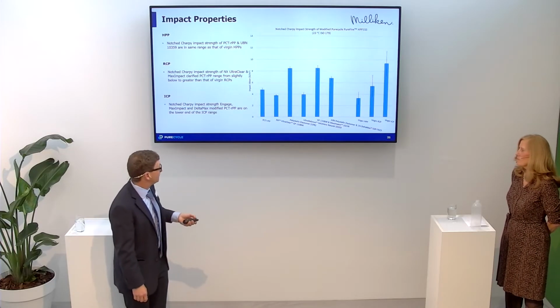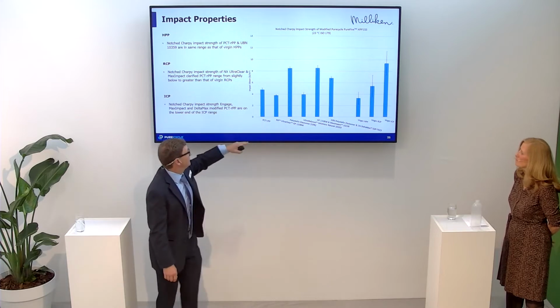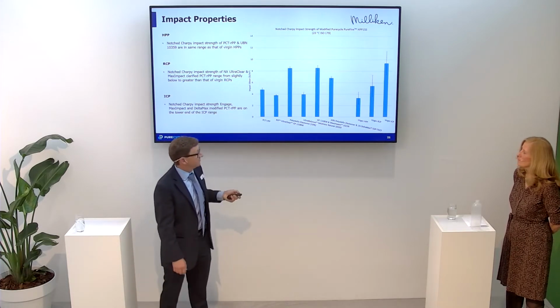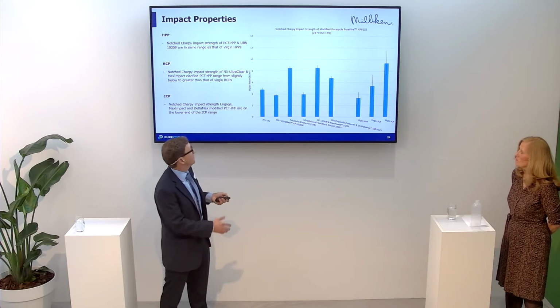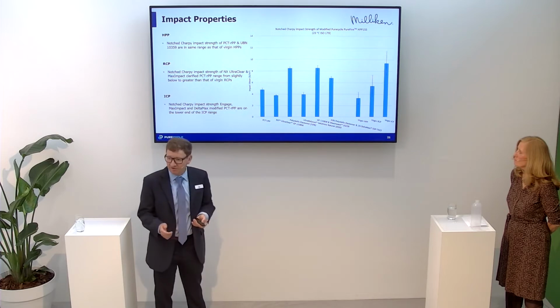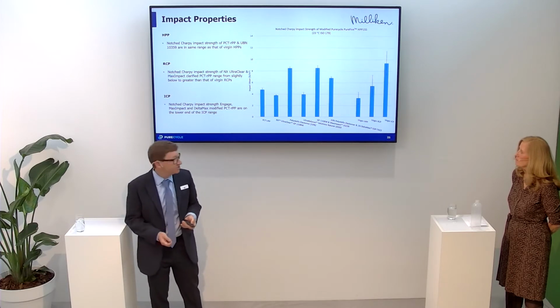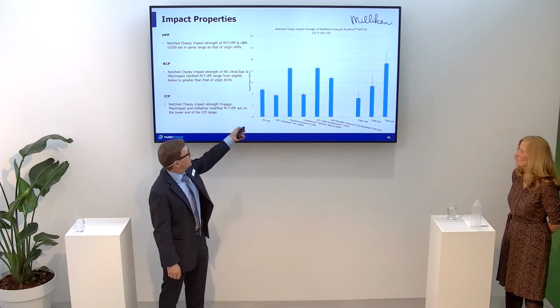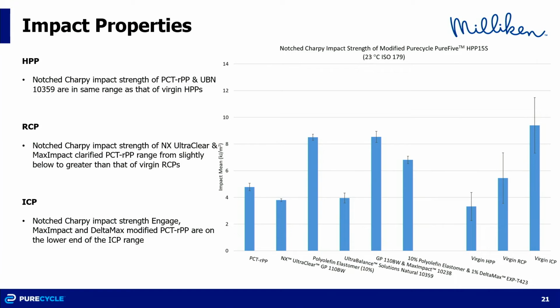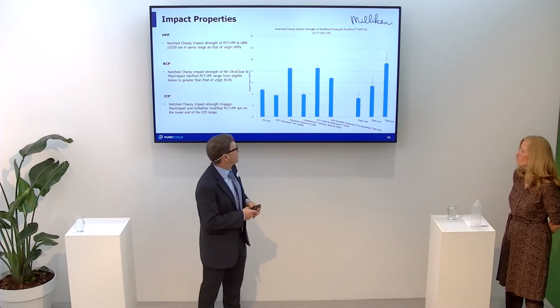Finally, impact properties. The material as received with the nucleating package is a little better than a homopolymer, at about 5 kilojoules per meter squared in a notched Charpy at room temperature. The clarified sample is a little bit lower, at 4. But again, it's still in the range of virgin random copolymers.